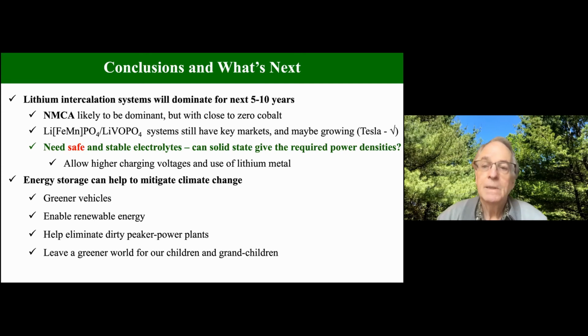At the moment, the present carbonate electrolytes have a number of additives in them to stabilize them, but even so, they're still not stable. They react too much, there's still some dissolution. So we need more research on the electrolyte. And I think the question is still out, can solid state give the required power densities at reasonable temperatures? Now, in vehicles, you don't really want to go much above 30 or 40 degrees. I think for grid storage, you can in fact use 60 or 70 without too much problem. If we had stable electrolytes, we could potentially go to higher charging voltages and use lithium metal.